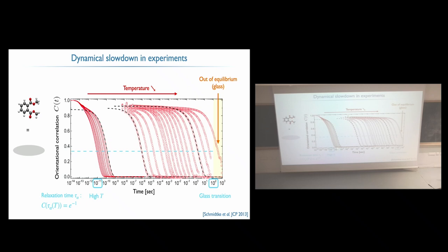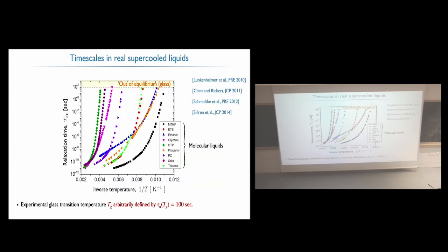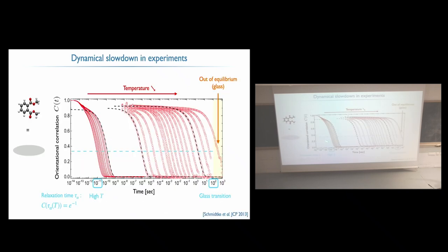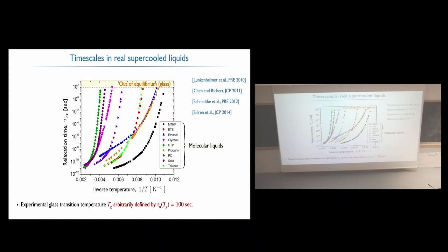So those are some of the timescales I really wanted to highlight here. You have very, very fast, you have 10 picoseconds when the liquid is very fast, and it goes to 100 seconds. So that's really dramatic. And one way to show this in a more compact way is to plot this relaxation time. So again, the time at which this correlation hits a plateau. Since it's the same form, you can just take this as the relaxation time. And typically this is plotted in this plot here: the relaxation time in log scale as a function of the inverse temperature.